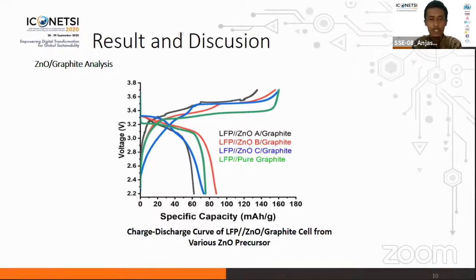Based on the figure, the highest initial specific discharge capacity of 88 mAh per gram was obtained by the cell with ZnO-B graphite anode, which is higher than the capacity of the cell with pure graphite as anode. However, ZnO-A and ZnO-C have lower capacity compared to pure graphite. The reason behind this phenomenon is still unsure. However, based on XRD analysis, it appears that the precursor characteristics affect the final capacity.